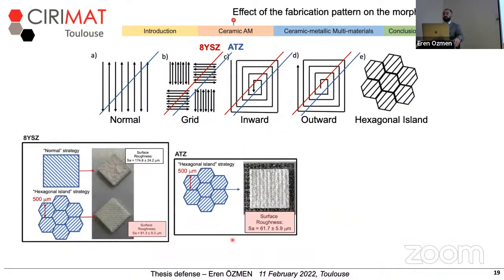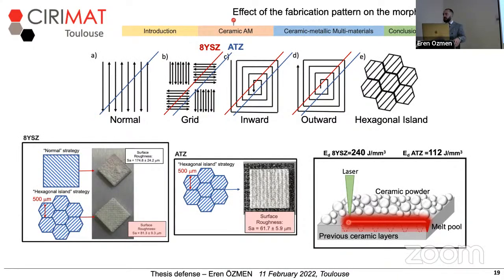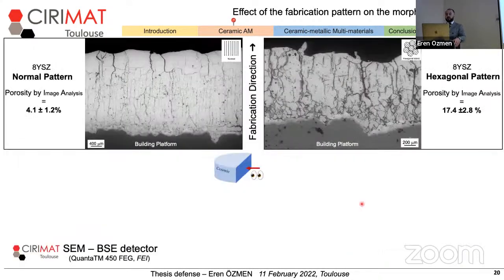One explanation for this can be the melt pool, which is created during the lasing process. As the energy density needed for ATZ fabrication is almost half of 8YSZ, it might be creating a less deep melt pool, and that can be decreasing the surface roughness on ceramic pieces. When we check the effect of fabrication pattern on the vertical polished cross-section of pieces, I first compare 8YSZ pieces fabricated with two different strategies. When I process these scanning electron microscopy images with the image analysis software ImageJ, I see that the porosity in the hexagonal pattern piece is almost 4 times that of the one fabricated with the normal strategy.